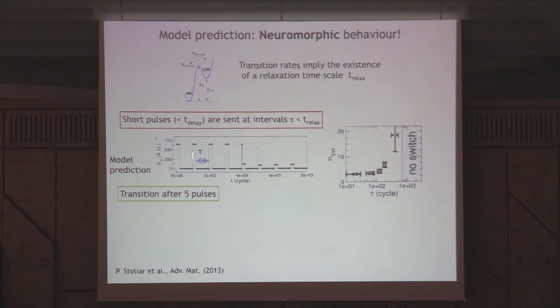You study that systematically as a function of the time between the pulses, and you have this phase diagram, in which at very long times there is no switching, and at very short times you have the minimum number of pulses required for that given voltage, which in this case is 3. Then you increase the time, you need more pulses until you see this diverges, until beyond a certain threshold you don't see switching anymore.